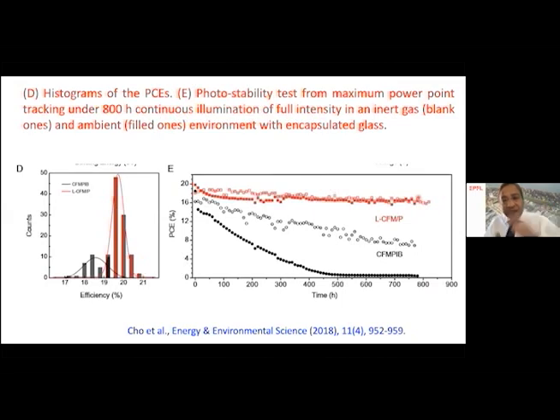And the same cell encapsulated with glass to glass is shown as the filled squares, overlapping with the inert atmosphere conditions. Under the same conditions, however, without the layered perovskite, that's the two-dimensional perovskite on top of three-dimensional perovskite, you can see the stability under glass sealing is decreasing significantly, and under argon atmosphere also is decreasing. So the beauty of this two-dimensional perovskite acting as a protecting layer is demonstrated here amply, protecting the perovskite layer followed by increased stability. And also we can see reproducibility of this configuration is significantly higher compared to the previous reference samples.